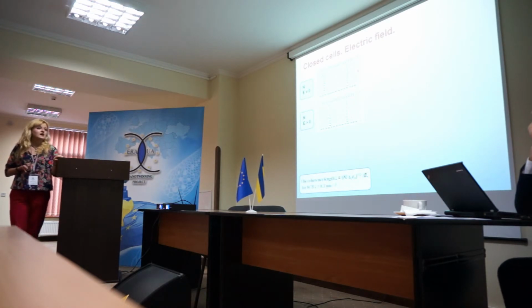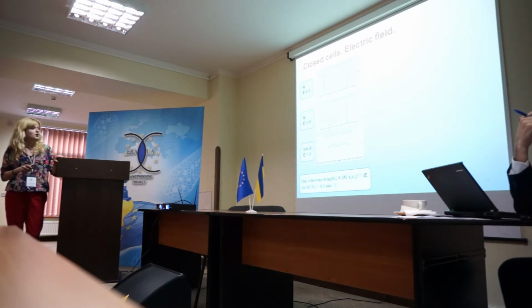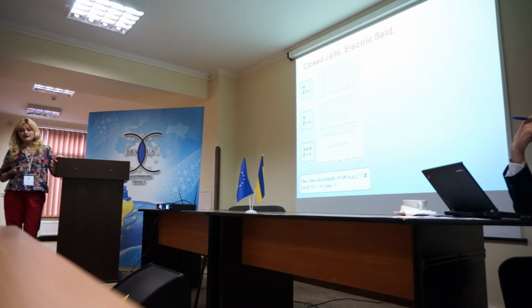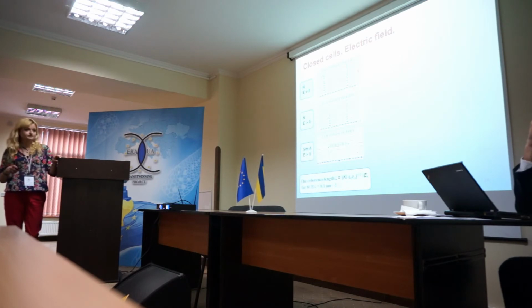toward the surface inducing planar anchoring. In this case, when we further decrease the temperature so that we have a transition from the nematic to the smectic A phase, in the region that was homeotropic, flat layers will be formed. And only in the regions where the director field was tilted, a linear defect array will form, so that applying the electric field has an effect similar to compression, where we just reduce the thickness of the smectic A film that is viable for linear defect creation.